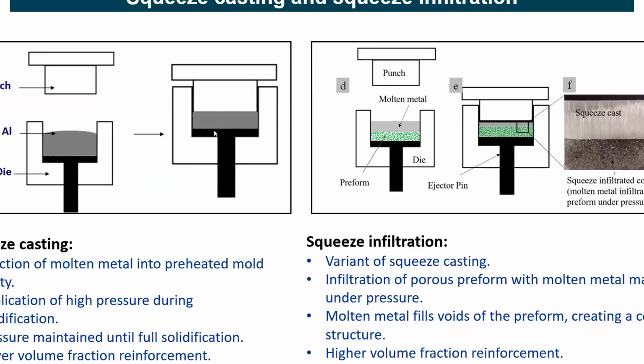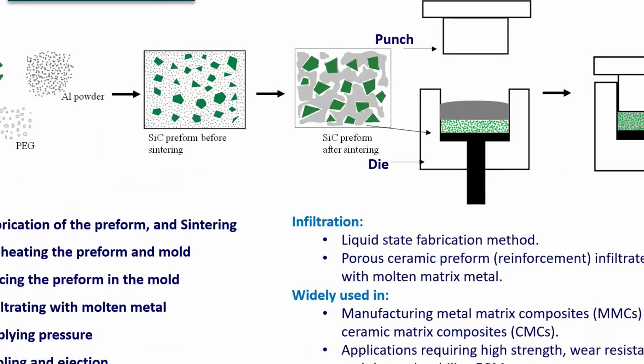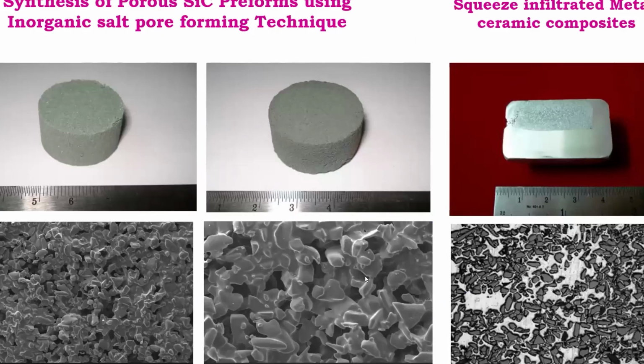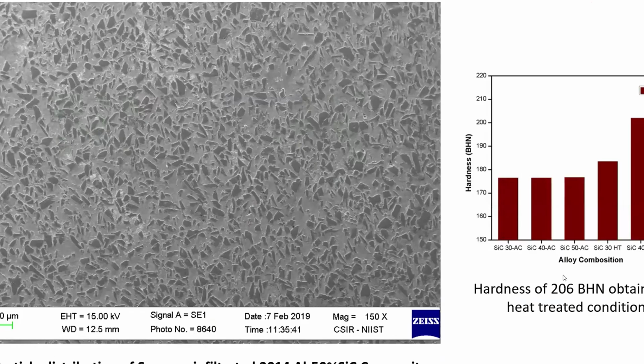So this is squeeze casting, as I had informed earlier. This is how the preform is made. You have the particles, you have the polymer or something, and binders. Then you make a green compact and sinter it. You will end up with porosity, and this porous body is kept inside the die and infiltrated. So this porous body looks like this. It's a green sintered body, and after leaching with salt we can leach it out. If it's a polymer, we can burn it out. You will get a porous body like this with all the SiC reinforcement, and you can get a reinforced composite of this type.